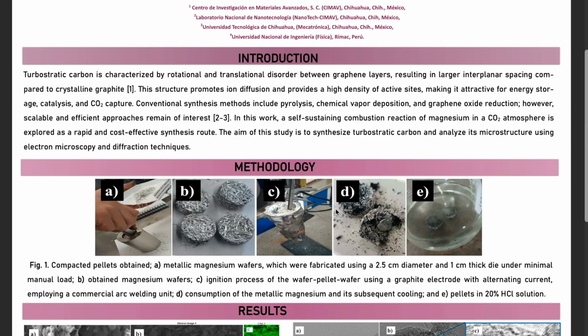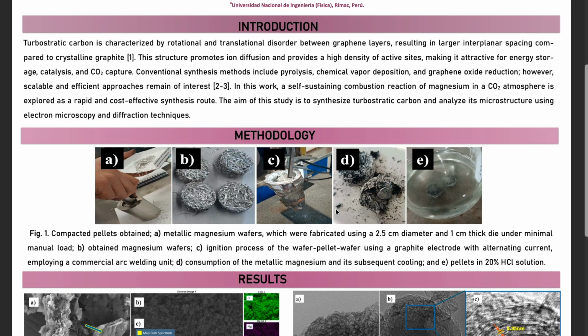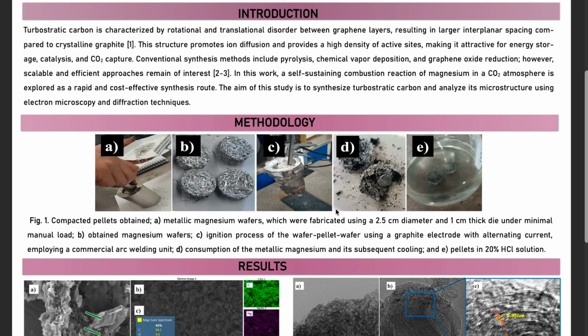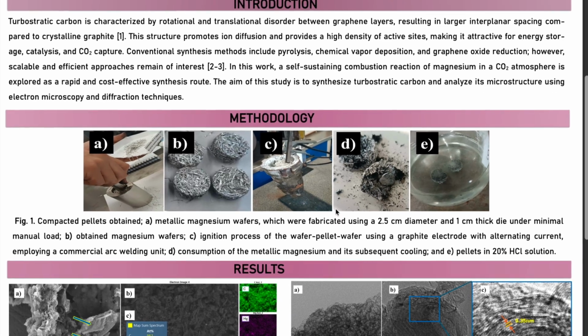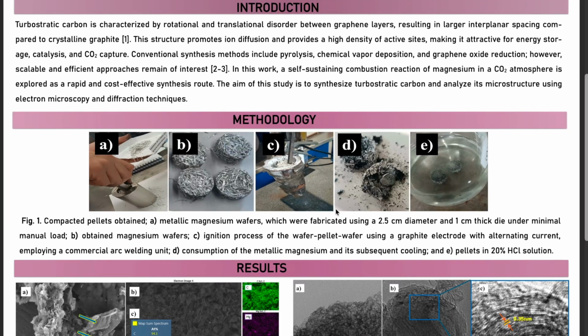Moving on to the methodology, shown in Figure 1, the experimental procedure follows a straightforward sequence. In panels A and B, we prepare the precursor by fabricating metallic magnesium wafers, 2.5 centimeters in diameter and 1 centimeter thick, using a die under minimal manual load. Next, as illustrated in panel C, we initiate the reaction by placing the magnesium inside a carbon dioxide environment and igniting it using a graphite electrode powered by alternating current from a commercial arc welder.